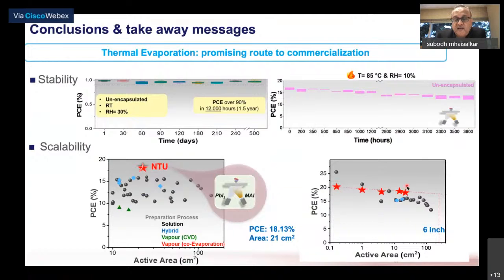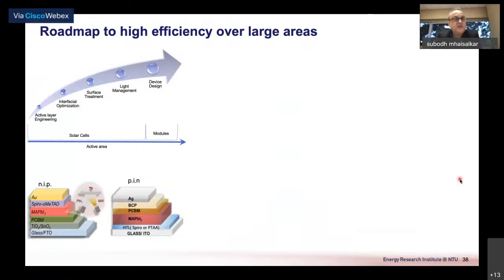The red stars are our data. As we scale, you can see that the evaporated solar cells do drop a little bit, but do not drop as much as the solution processed devices. For the solution processed devices, the drop is much steeper. So really, we are intending that when we scale up to 6-inch, we would like to target high performance, and what that high performance would look like, I will also touch upon in the slides to come.